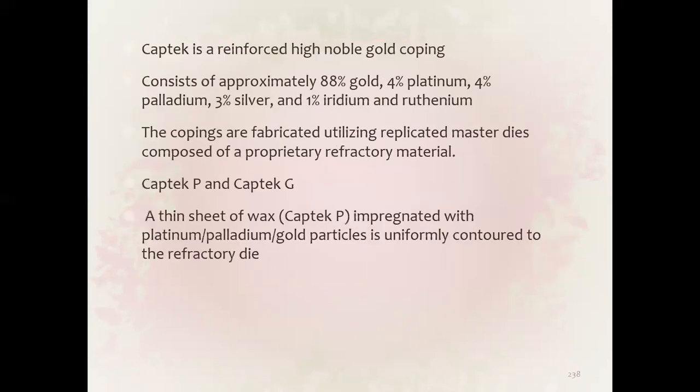The Captek system is a reinforced high-noble gold coping composed of approximately 88 percent gold, 4 percent platinum, 4 percent palladium, 3 percent silver, and 1 percent iridium. Examples are Captek P and Captek G.